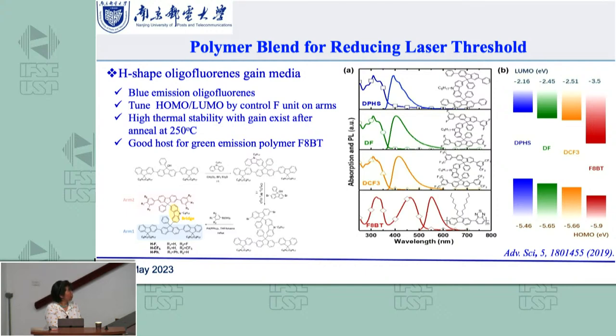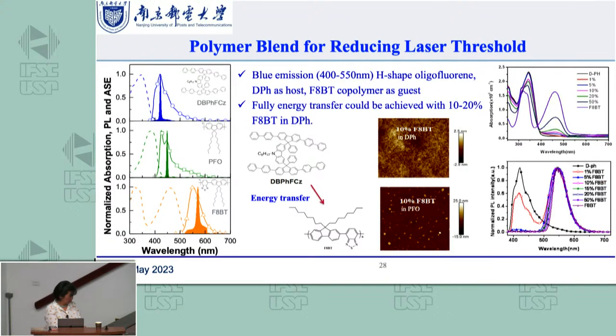And also, when you slightly change the structure, the HOMO-LUMO level also can be tuned. So we especially choose this one, similar to that. We always compare the blue emission material with the PFO. The absorption and the emission are similar to PFO, but we can use this as a host and F8BT as a guest. Put this together, from 1% until 50%, you can see the absorption of F8BT change like that.